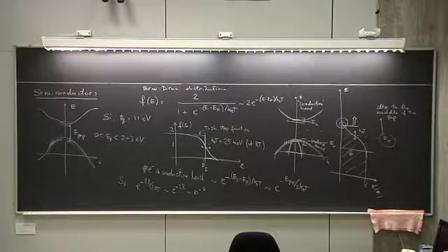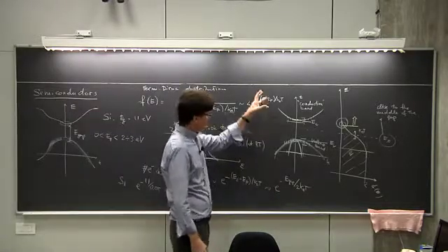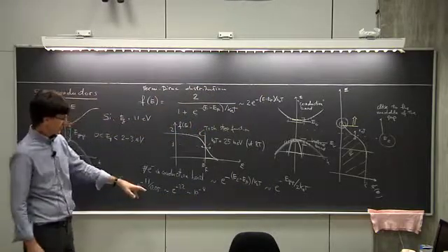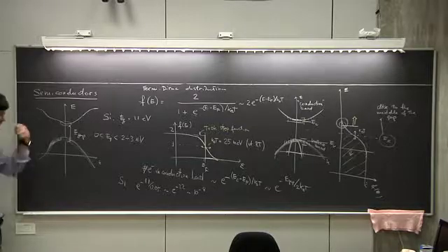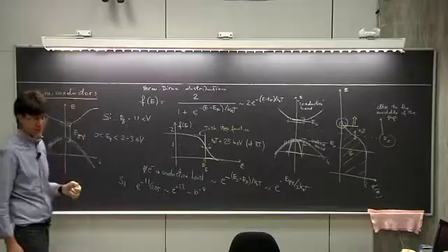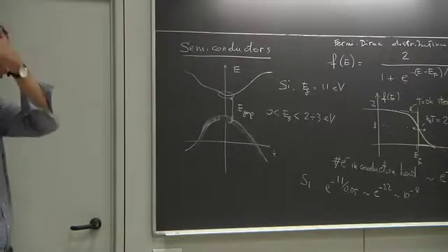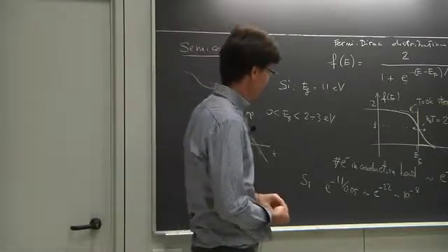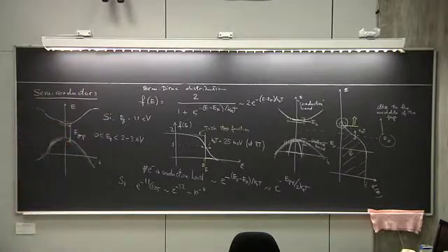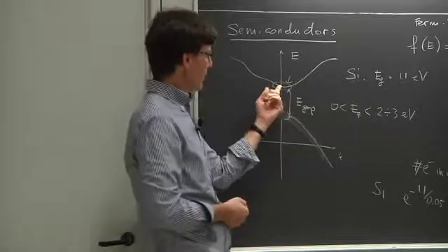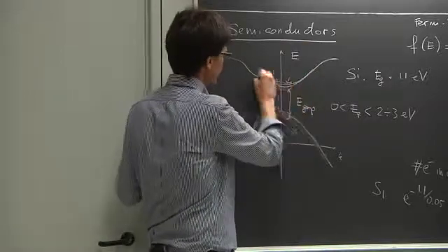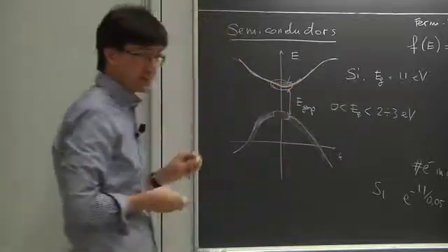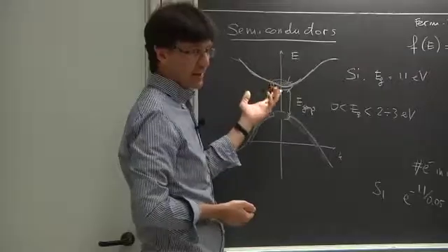In some units. Or if you wish, regardless of the units, there is something of the order of 10 to the minus 8, 1 out of 10 to the minus 8 electrons is promoted in the conduction band due to temperature. Now, you might think that this is a small number, but this is actually detectable. And if you have a small but finite number of electrons being promoted in the conduction band, these electrons will behave like free electrons, right? Because you now can think of this as almost like a free electron band, where the electrons are located close to the bottom of this free electron band. Okay, so they will behave like a metallic system.